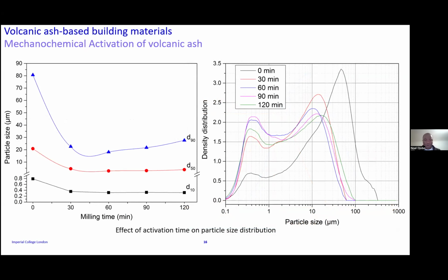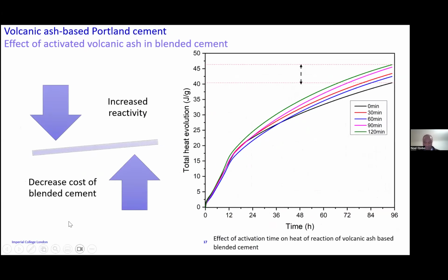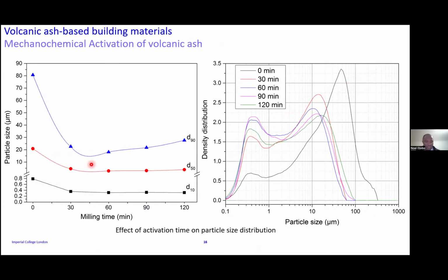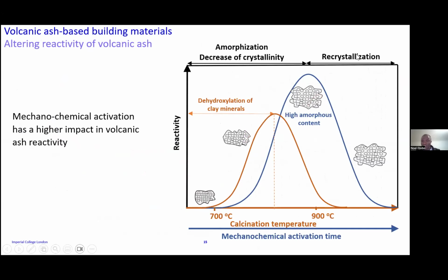Here, for example, we have the effect of the mechanochemical activation on the particle size distribution of the volcanic ash. As one can see here on the left, when you ball mill volcanic ash for different time, you initially have a significant reduction of the size of the particle and then an increase with milling time. That is what we call here the recrystallization, or the agglomeration.